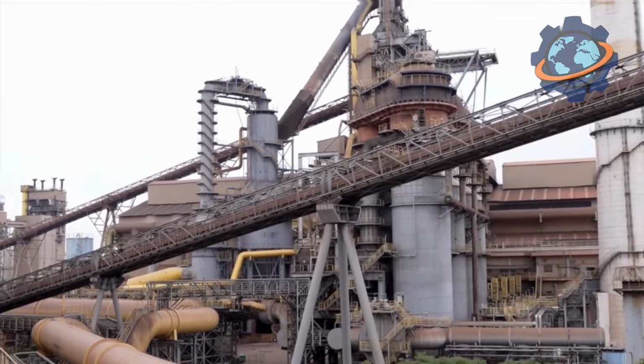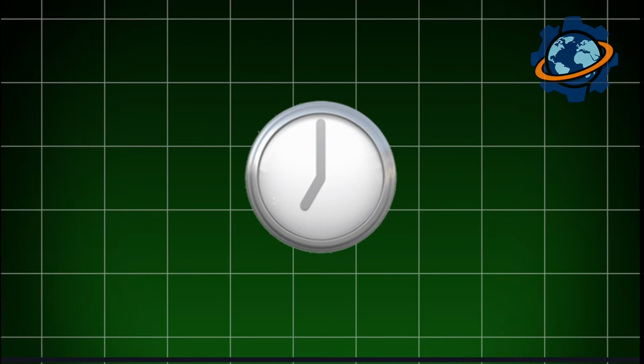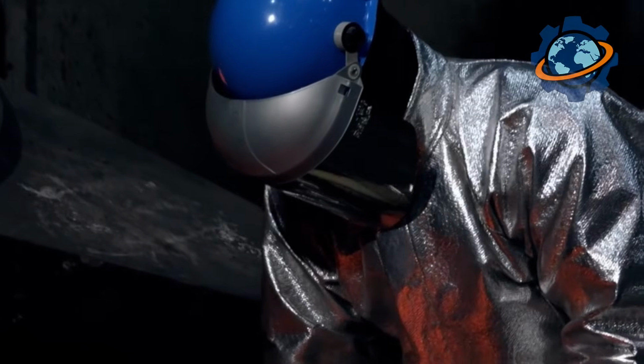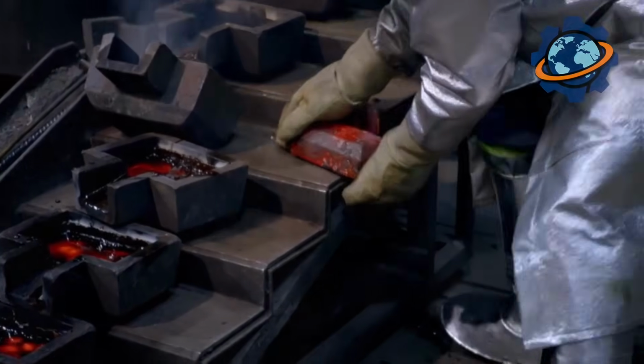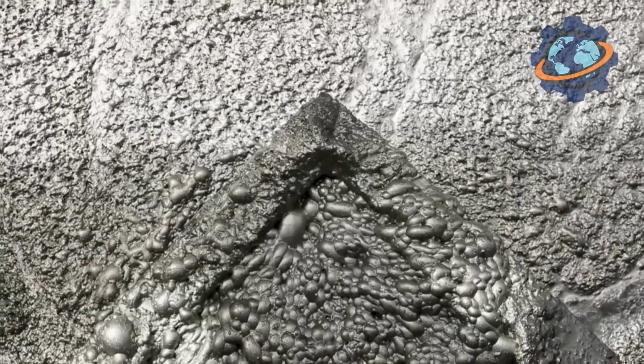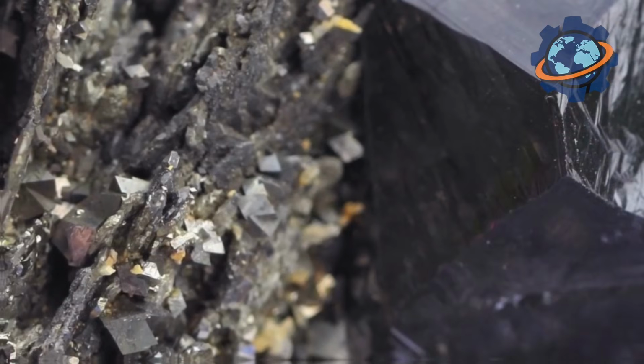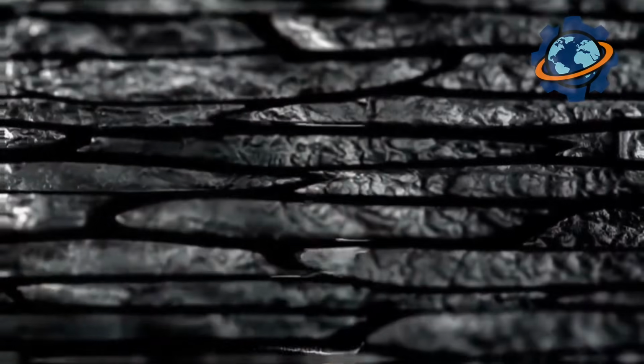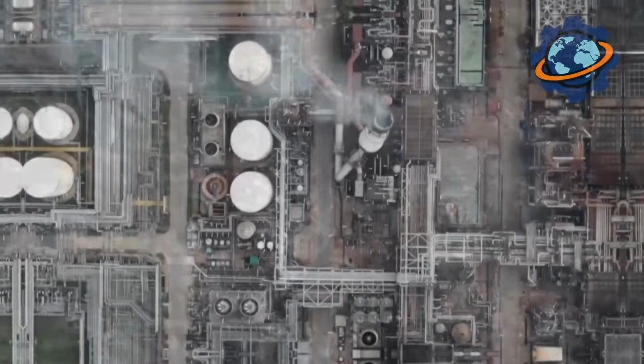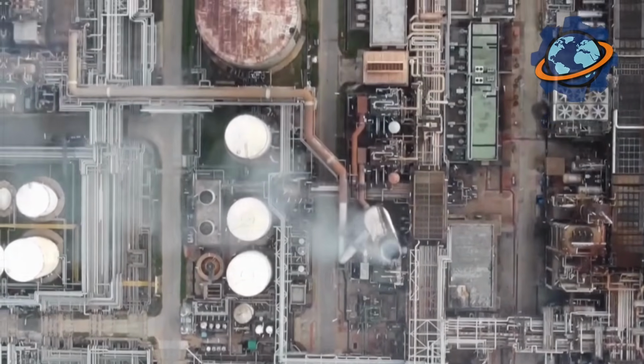This layer bonds permanently to the steel. On top, a layer of pure liquid zinc. The beam is held in the bath for 1 to 2 minutes. Then it's pulled out. Excess molten zinc drains back. In air, the coating quickly solidifies. The surface becomes silvery, matte, with the characteristic pattern of crystals, zinc flowers. Coating thickness from 2 to 8 thousandths of an inch. That's just fractions of an inch, but it's enough. The galvanized beam won't rust for 50 to 70 years. Even scratches aren't scary. Zinc continues protecting.